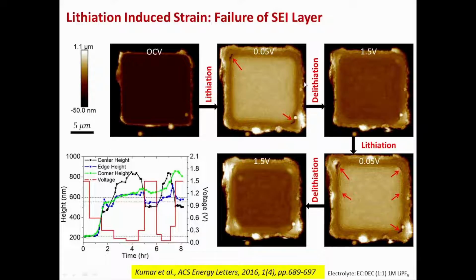But what you can see is that as we lithiated, there is some appearance of nano and micro cracks at the edges and corners of these islands, and when we delithiated, these cracks kind of close up, and some kind of delamination also results.